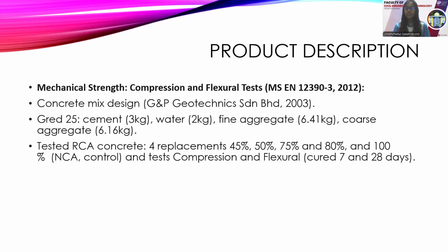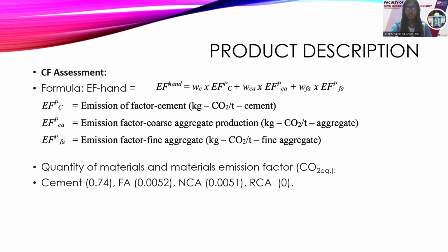First 45%, second 50%, third 75%, fourth 80%, and lastly we compare with the natural coarse aggregate, which we call the control sample without any replacement of RCA. They were tested for compression and flexural test after curing 7 days and 28 days.